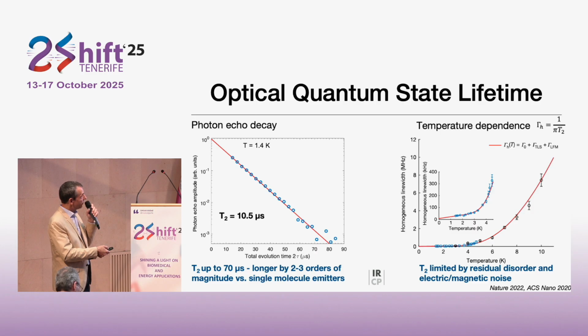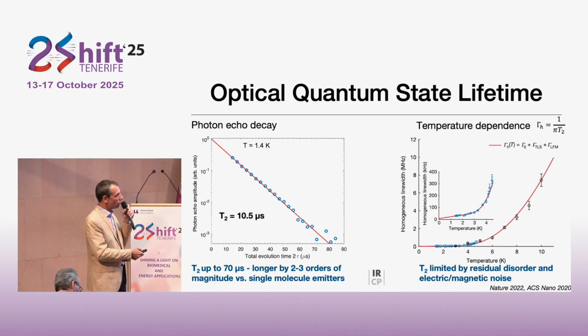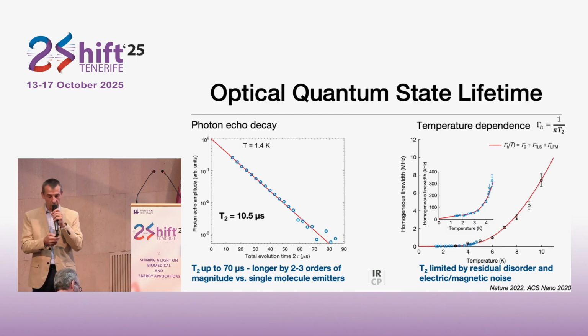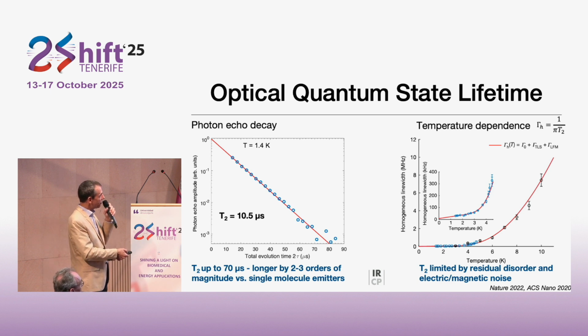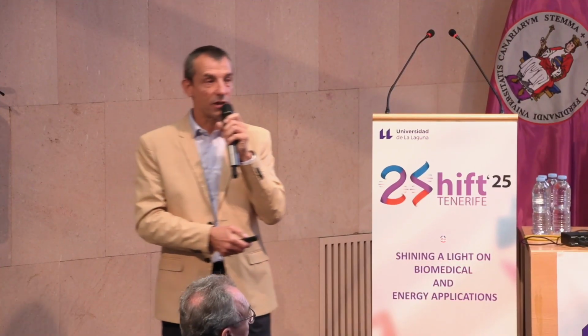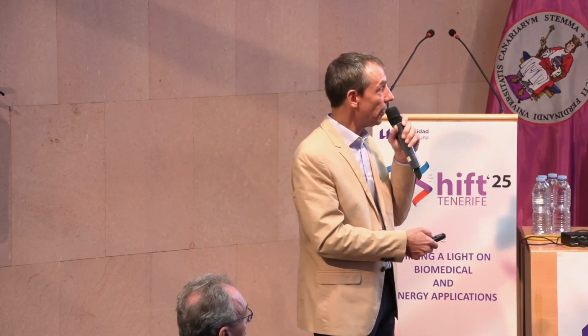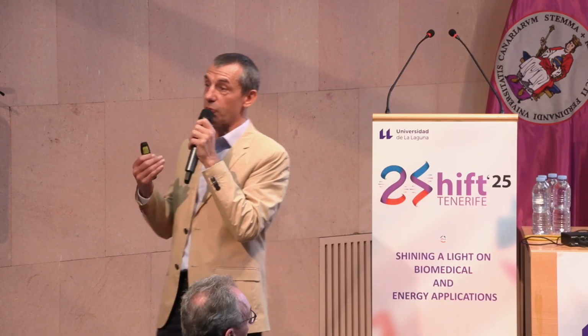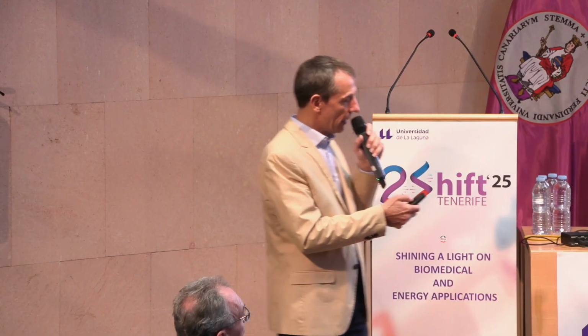Now there is also a term which seems very small on this scale, but actually it's not so small. This is more or less the 70 microseconds we measure. So how can we do better here? Well, we have a contribution which seems to be essentially temperature independent. To identify what is causing this perturbation, it's not completely clear at the moment, but we suspect electric noise, because we already saw this contribution in rare earth nanocrystals, for example, and probably also magnetic noise because we have the nuclear spin of the protons in the structure. This is likely also to perturb the quantum state. And we believe these are the main contributions to this limitation to 70 microseconds.